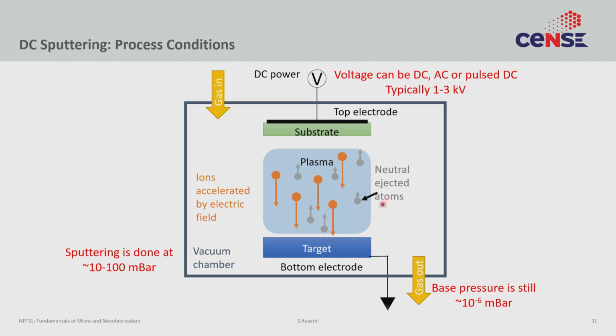So what you have is a plasma somewhere in the middle, and argon plus ions are coming down. The neutral ejected atoms are going towards the substrate. You need some gas in because you need the source of argon. So the argon gas is pumped through some MFC from the top, and somewhere from the bottom, you have a pump that maintains the vacuum. Typically, the base pressure is maintained at high vacuum conditions, so around 10 to the power minus 6. But because you are continuously flowing argon during the deposition process, the actual pressure is a little higher, around 10 to 100 millibar.